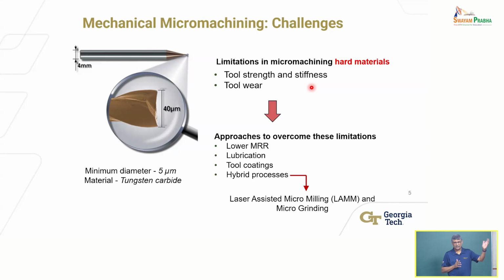But what you can buy commercially, maybe up to 25 microns in diameter, right? With 1 or 2 flutes or cutting edges on an end mill. You can see one picture here of a typical end mill. Looks like a conventional end mill except scaled down in size, on the order of about 40 microns. Only a small portion, the tip, is where the cutting flutes are. So you're restricted to making small scale features in this.